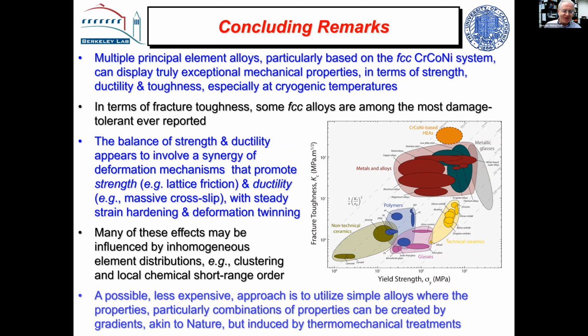Professor Ritchie, thank you for this lucid presentation indeed. Thank you so much. I learned a lot today. I'm sure everybody in the audience feels the same as I do. Regarding these FCC high entropy alloys, because essentially they don't have any microstructure like traditional alloys, is it possible that the presence of the short range ordering activates the motion of dislocations into planar slips? And then once the dislocations are activated into planar slip modes, then all the other mechanisms have to follow up. Could there be something like that?